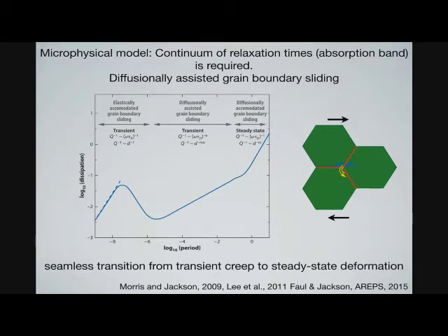with increasing time scale. That's what's called an absorption band, so that you should see a frequency-dependent behavior, and the seismologists are still working on that. I mean, there are certainly experiments going in that direction, looking at the frequency dependence of this attenuation, which is what the data that's out there is a confirmation of, essentially what we see experimentally, in that this exponent of this frequency dependence is similar, observed seismically, to experimentally. The exponent is about 1/3. That's when you do seismic experiments, which are very difficult because you have to measure the same wave at different frequencies. It's roughly the same exponent.